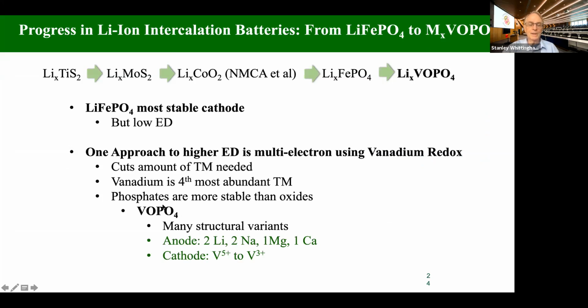Another advantage of looking at this material, there are at least 7 different variants. And so we wanted to look at the different structural types. We had the option then of using 2 lithium, 2 sodium, 1 magnesium, or 1 calcium. Here I'll only talk about the 2 lithiums. I will mention that our colleagues at Toyota looked at our material with magnesium, and you have to realize magnesium is, I call it the selfish element. It goes to the structure and says that oxygen ion is mine, and it takes it out and forms magnesium oxide.